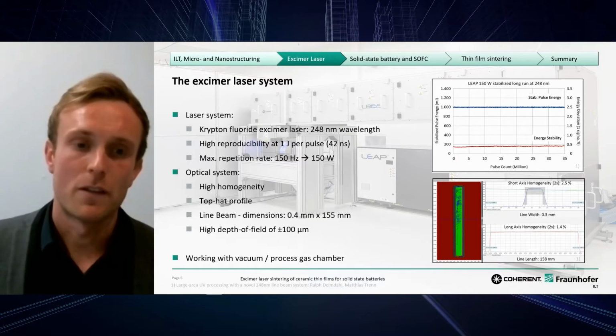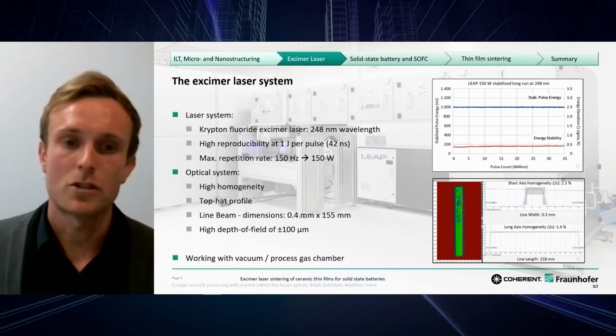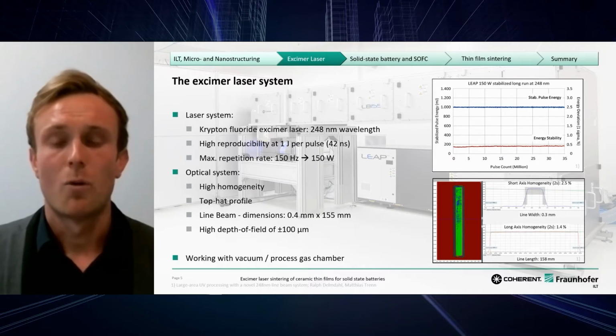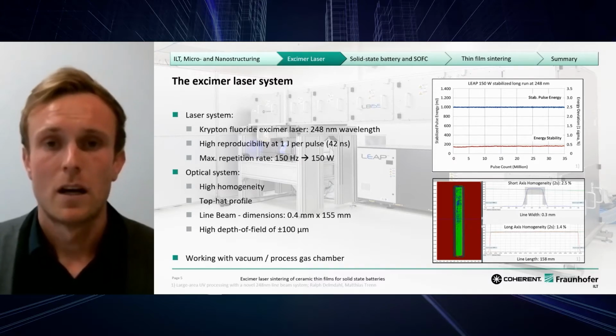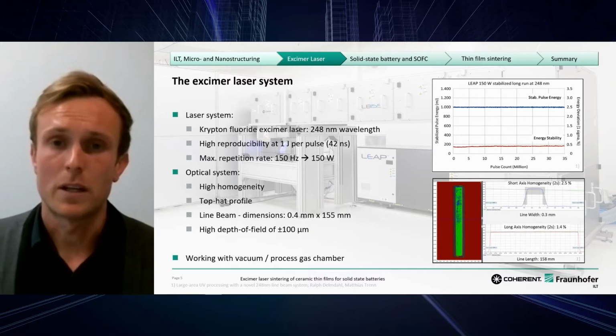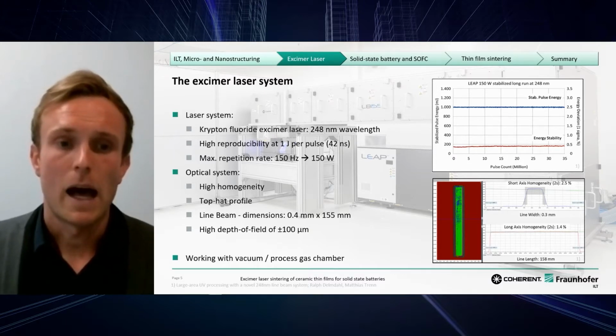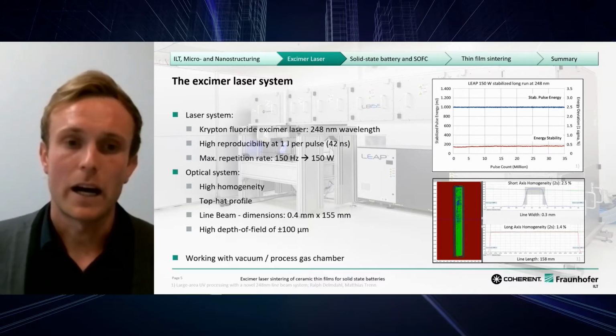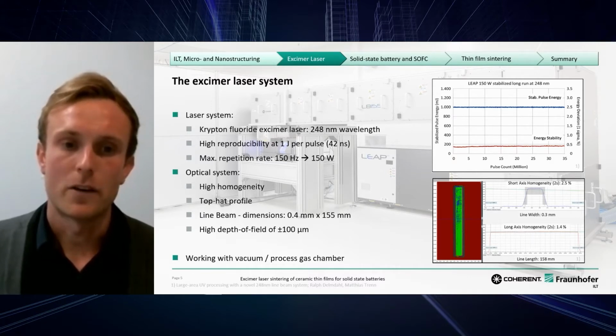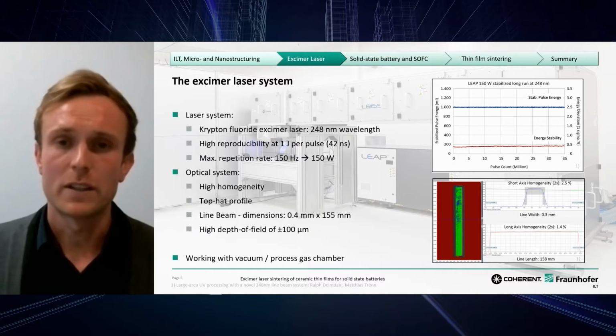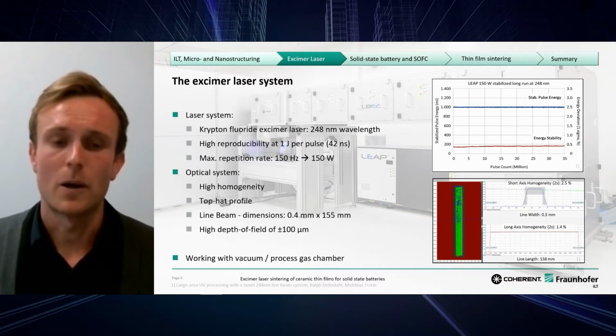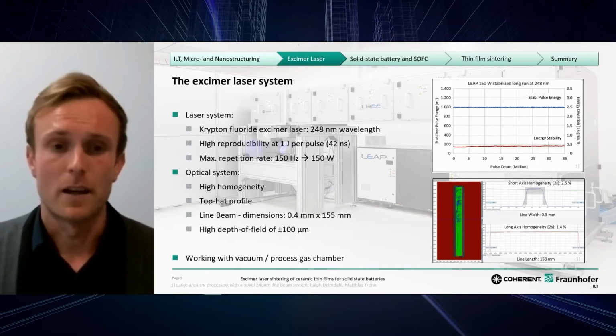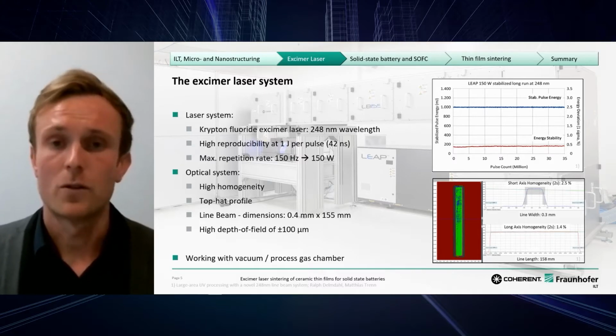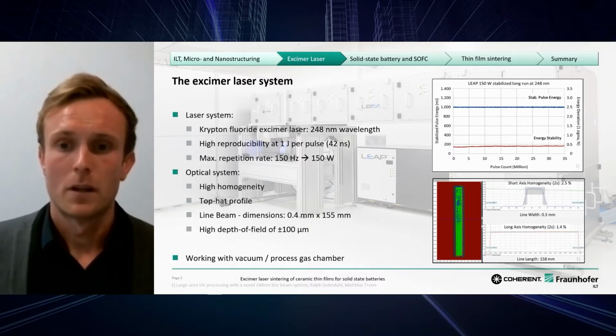Another unique characteristic is the optical system. First of all, to mention the top hat profile with a line beam dimension of 0.4 times 155 millimeters. That's pretty huge compared to a commonly used laser system. And with its high homogeneity shown at the bottom right and its very large focus field, we can process large-scale samples, which is very good, also with a vacuum or process gas chamber.